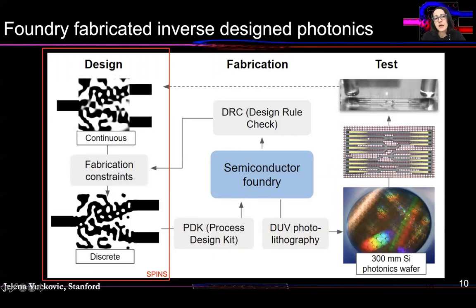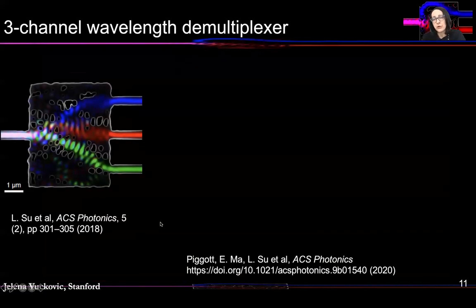So here is one of our early results, done in collaboration with the group of John Bowers from UC Santa Barbara, using the AIM Photonics foundry for silicon. It shows that in a foundry, we can implement photonic inverse design devices and circuits with exactly the same properties as the ones that we initially fabricated using electron beam lithography and other parts of the process at the academic fabrication facility. Again, it's important to incorporate design rules from a particular foundry process. But once you do that, you can design your devices, send the layout to the foundry for a tape out, and you receive your devices back, which you can measure. We did that for many, many different devices.